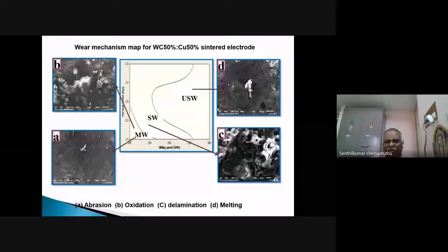and a normal load of 3.5. So the melting takes place at this sliding speed and higher sliding speed and higher normal load. Finally, the seizure takes place because of the friction between the disc and the pin material. More energy is generated, that is, more temperature is generated between the disc and the pin. The seizure takes place, and also the melting of the metal takes place. Finally, the seizure occurs.